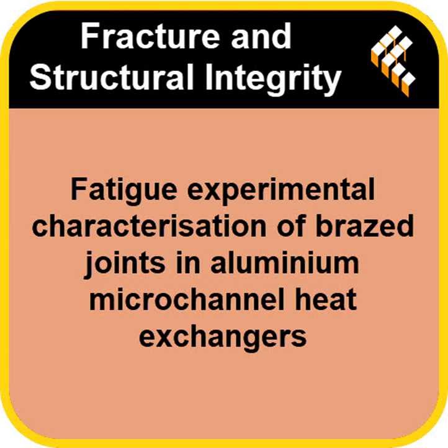10 million cycles. And how did they determine the actual fatigue limit? They used a specialized testing procedure called the staircase method. It's designed to efficiently zero in on the stress level where roughly half the specimens will survive those 10 million cycles and half will fail. Okay. And the result, what was the limit? The estimated nominal endurance limit for 50% survival probability at 10 million cycles was found to be 60 megapascals, or MPa.